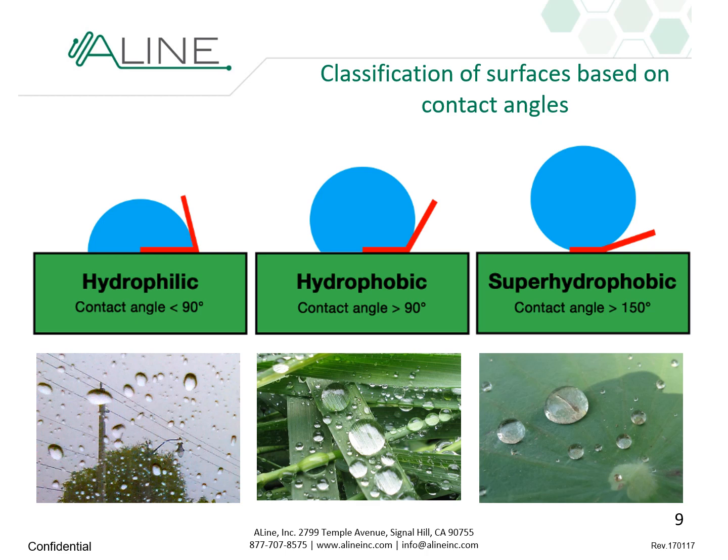An extreme case is when you add extra roughness to a hydrophobic surface, you get the superhydrophobic effect, which is the one shown here on the right, and which, as I said, can be exhibited by lotus, ginkgo biloba, or other plants, where the droplet contact is so small that by gravity it just rolls over, and you're not even able to stabilize it to measure a defined contact angle. It gets very tricky.